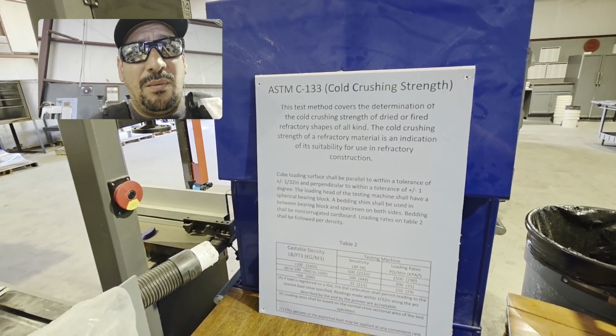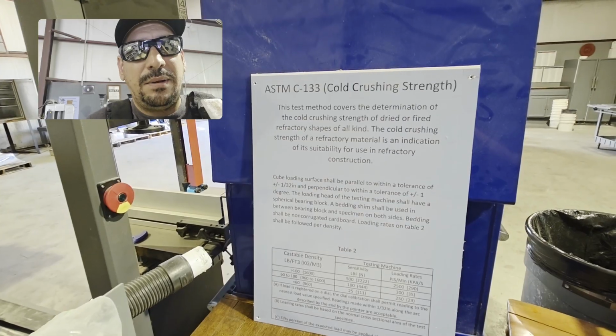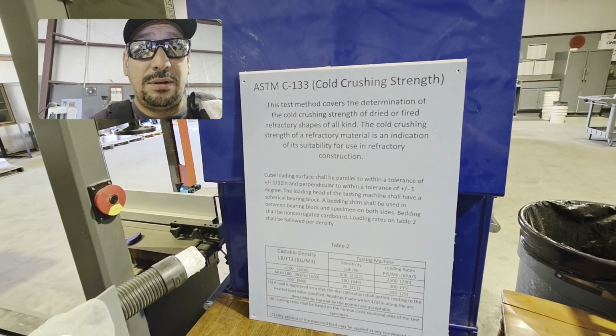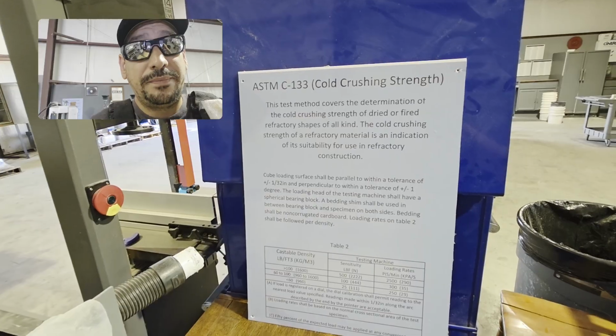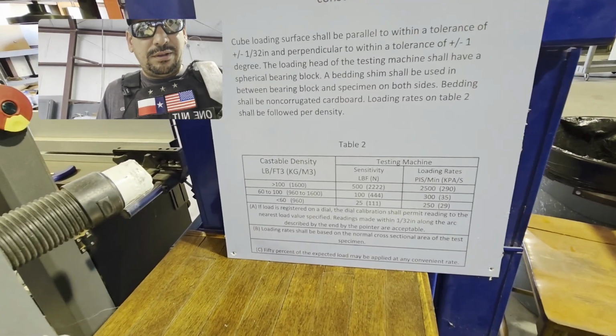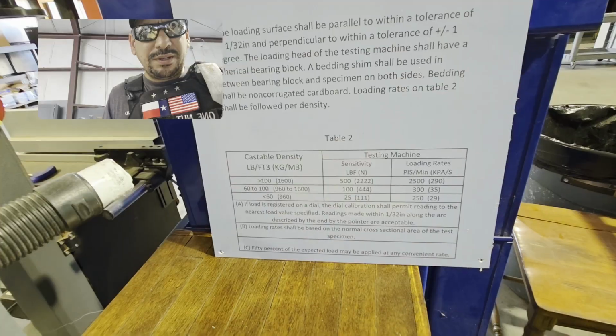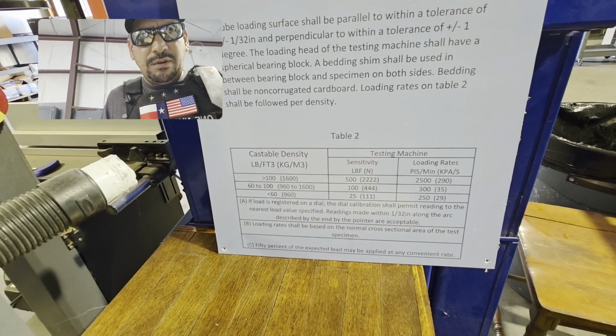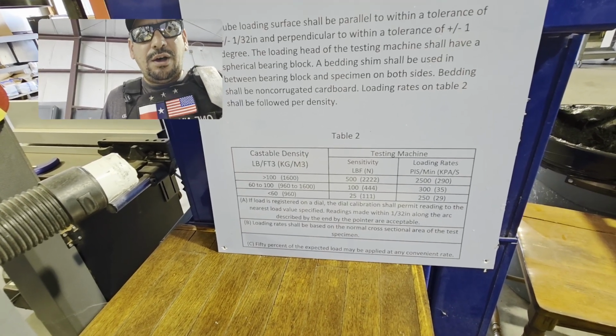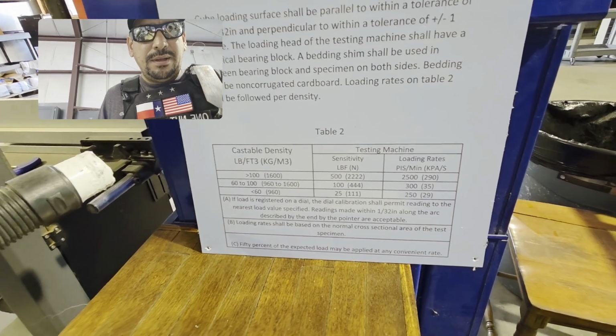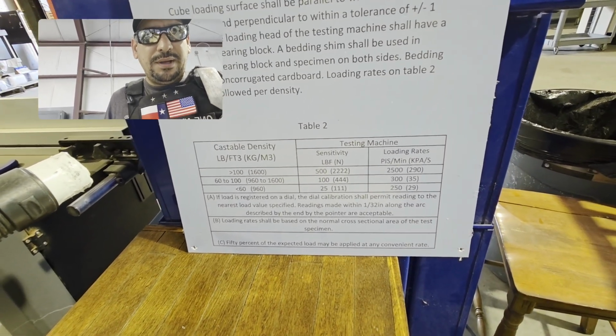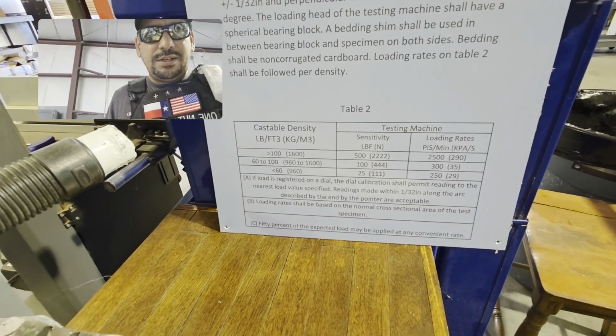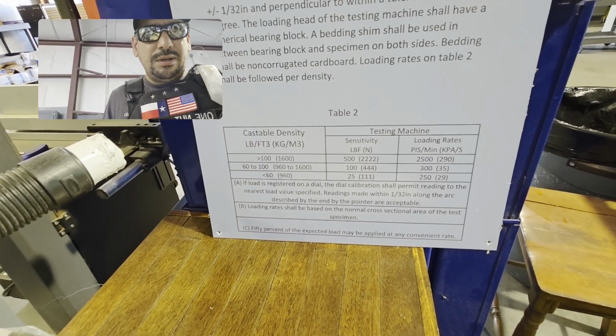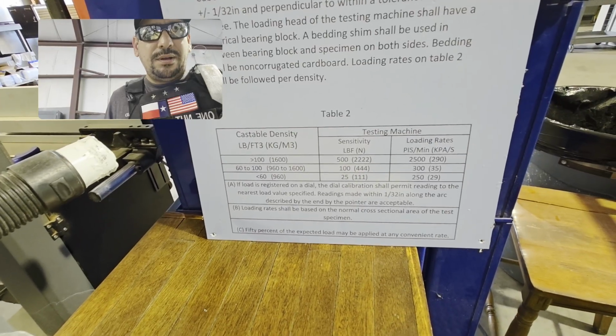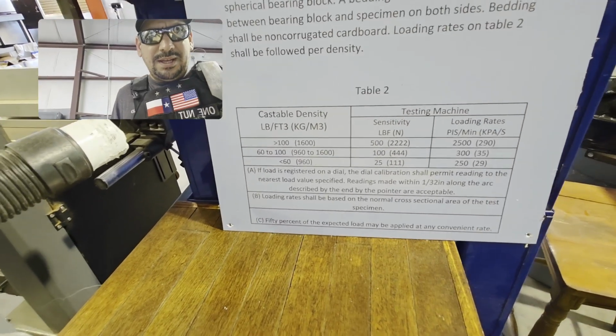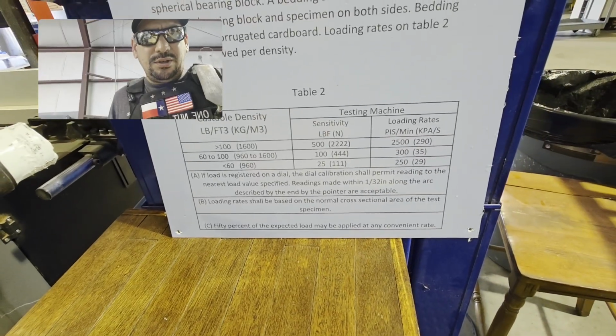So one of the things you're going to want to remember is the ASTM testing codes. For this case, the cold crushing strength is the C133. And this little chart down here looks very confusing, but all it's saying is, first one there, if your density of your material is greater than 100 pounds per cubic foot, then you're going to crush it at 2,500 psi a minute. Your density anywhere between 60 to 100 is going to be crushed at 300 psi per minute. Less than 60, you're going to go at 250.